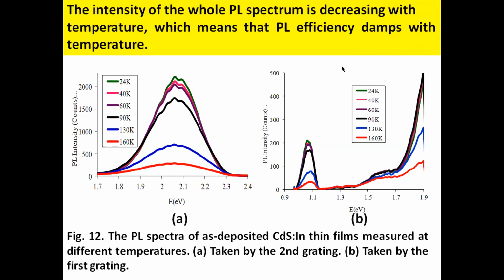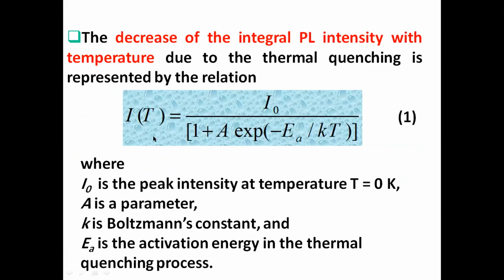Now the decrease of PL intensity with temperature can be explained by this formula, which relates the intensity of the photoluminescence with absolute temperature. In this relationship, I0 represents the intensity at 0 Kelvin, A is a parameter, K is the Boltzmann constant, and EA is the activation energy. Now the exponential factor in the denominator, when the temperature becomes high, becomes larger than 1, and the 1 in the denominator can be neglected.